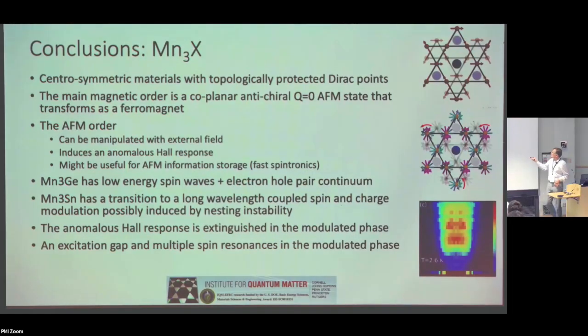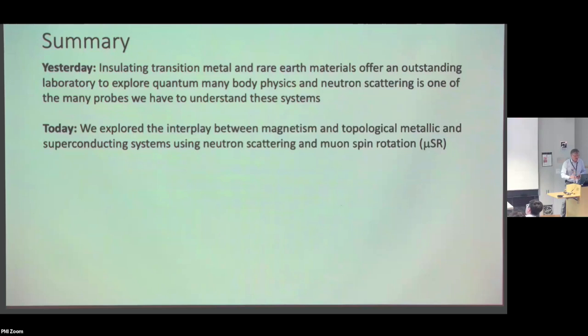We've analyzed this complicated incommensurate structure that actually eliminates the anomalous Hall response. And then just to summarize my stories here, yesterday we were talking about insulating transition and rare earth systems as really laboratories to study quantum many body physics. Using similar techniques, we can try to understand the interplay between magnetism and topological metallic systems. And I didn't get to talk about the superconductor, but in that case we were using muon spin relaxation to probe this kind of mixed type 1, type 2 system.